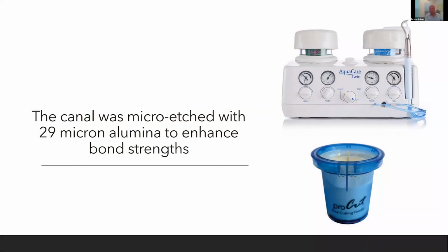There are many micro etchers on the market. This is actually purchased through Schein a number of years ago, called AquaCare. And the canal was micro etched with a particle size of 29 micron alumina. And the whole idea is to clean the canal itself. So you've taken out the gutta percha, and you know what it looks like. You got all that scraggly gutta percha in the canal. You got cement. You got to micro etch it to increase the bond strength.